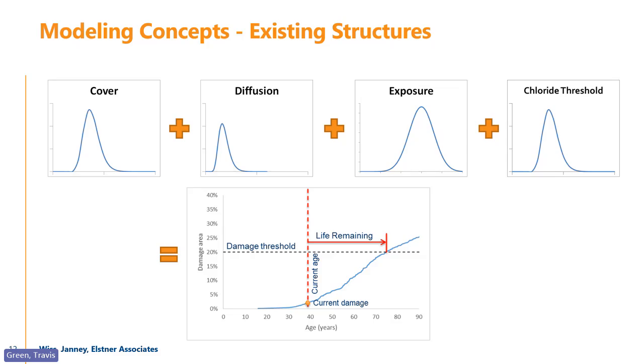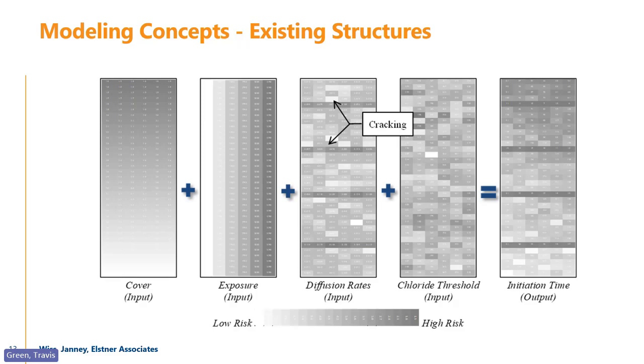We do some Monte Carlo simulations, and we end up with a curve like you see here, right? So we are in this curve, right? We're saying ultimately, hey, if we're here, we're going to see damage at 20% of this surface, at 75 years, right? And this damage area is basically spalling, essentially. And a lot of agencies use somewhere between 15 and 40% surface area as a trigger for some kind of repair work or removal and replacement work. I think this slide